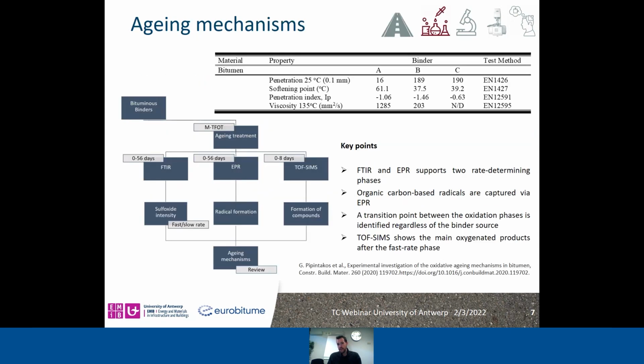I will jump now to the first core part of my presentation, which is the experimental proof of the aging mechanism that we have provided to some extent. For that reason, we have used three different binders that vary considerably from each other, not only in terms of empirical performance, penetration and softening point, but also in terms of crude source and distillation process. Binder C, more specifically from this table, is a product of visbreaking process, and also included waxes. So we tried to vary the binders as much as possible, so that we can conclude if the mechanisms are more or less universal or not.